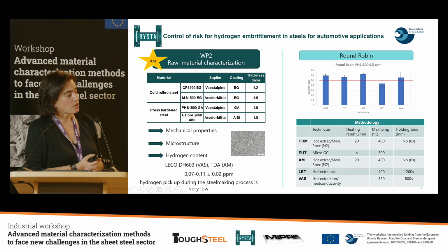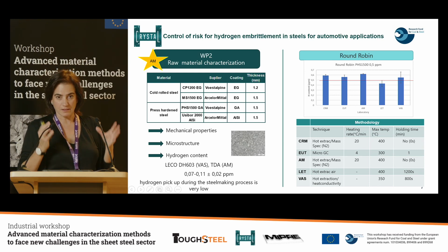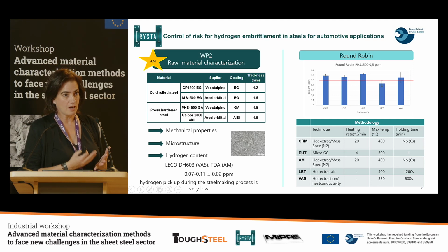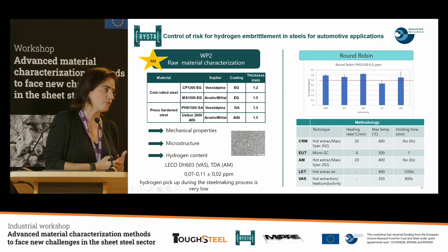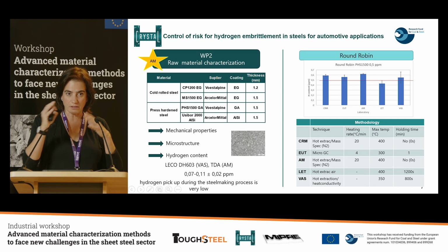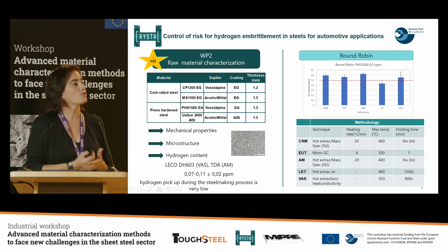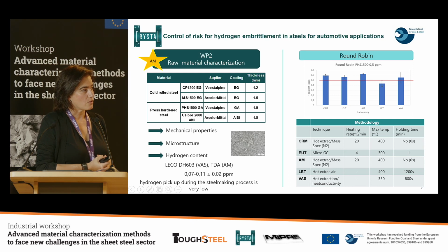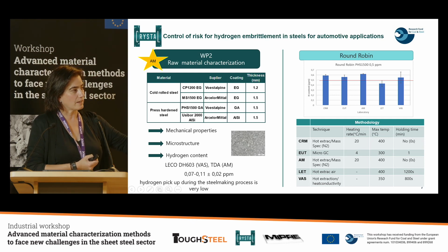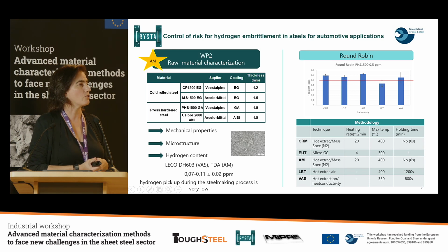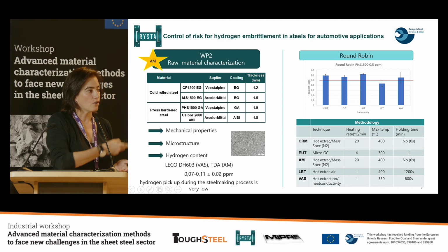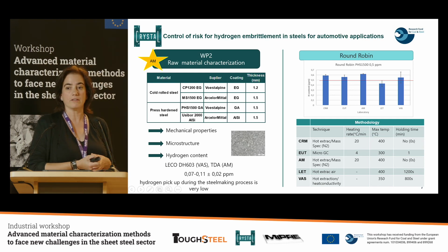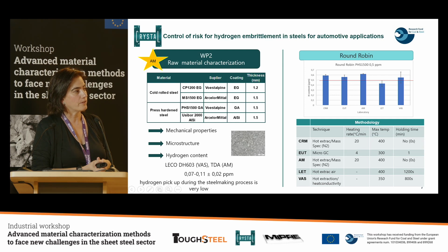Doing this hydrogen content characterization, we realized that inside the consortium we have 5 different laboratories with facilities to measure the hydrogen content. So we thought that it was very important to define if the hydrogen content measured in all the labs was more or less similar, or what the scatter was in this value. So in the table on the right, you can see all the techniques or the methodology that we have in our consortium. We can see that we have hot extraction, micro GC, hot extraction with different gases. Also, we have different heating rates, different maximum temperature, and different holding time.